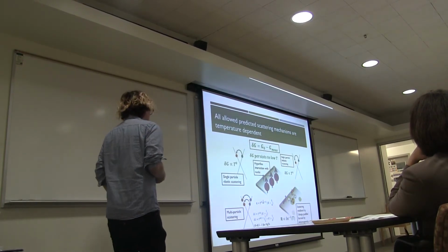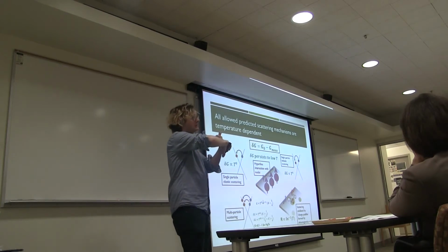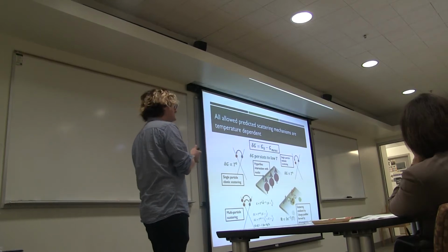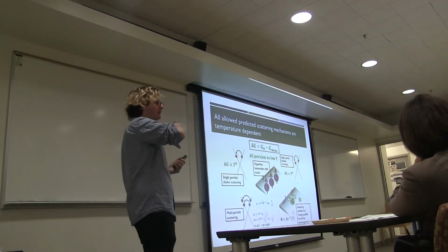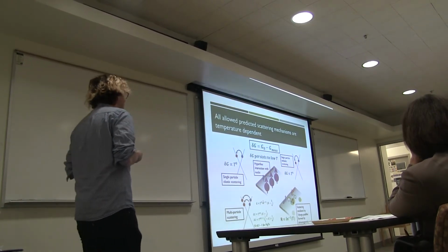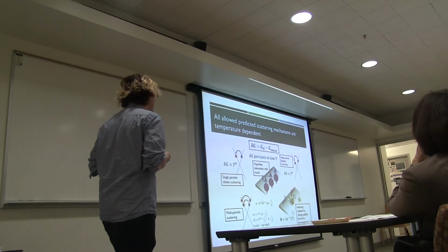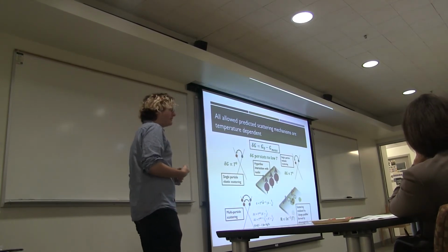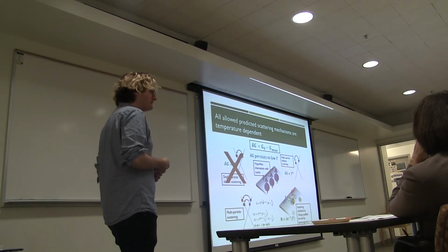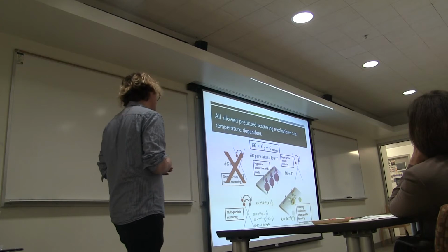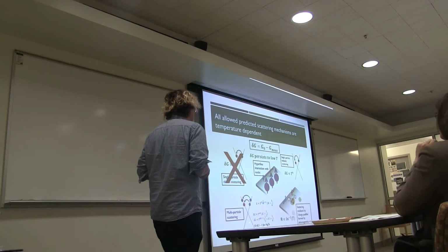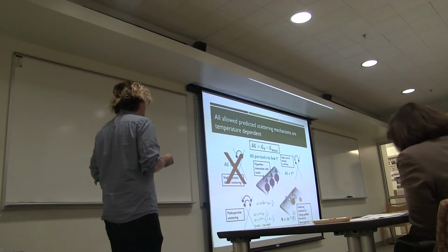So now we want to look back at this edge state, which has this weird spin structure, and think about what backscattering mechanisms are allowed. The backscattering mechanisms are different from what you'd expect for a typical 1D state because you only have spin up going one direction and spin down going the other. And so the easiest to understand mechanism for temperature independent scattering is single particle elastic backscattering. But this shouldn't be allowed in quantum spin Hall edge states, so we have to go look at other scattering mechanisms. So we can take into account inelastic scattering from phonons, or multi-particle scattering, or some more exotic things,